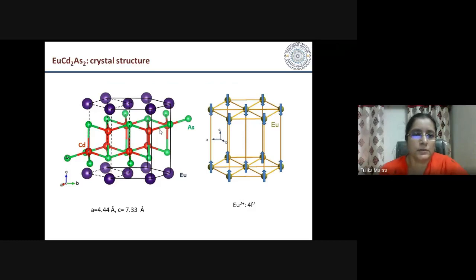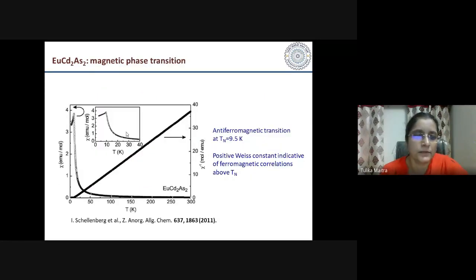So this is the crystal structure of EuCd2As2, where these Eu ions make a triangular lattice. Okay, so these are the Eu ions, the moments sitting on a triangular lattice, and this Eu is in the 2+ valence state with 7 electrons. So there is a large moment sitting here. These are the lattice constant values for this compound. Okay, this compound undergoes a magnetic phase transition from paramagnetic to antiferromagnetic phase at 9.5 Kelvin, as seen here in this experiment.